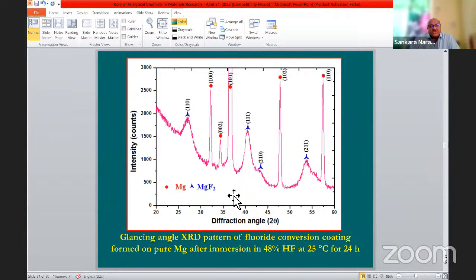And we cannot use a normal powder X-ray diffraction pattern to determine the composition, the various phases present in the material. So in these cases, glancing angle XRD is very useful. This is the glancing angle XRD diffraction pattern of a fluoride conversion coated magnesium sample. So you can index it very clearly.